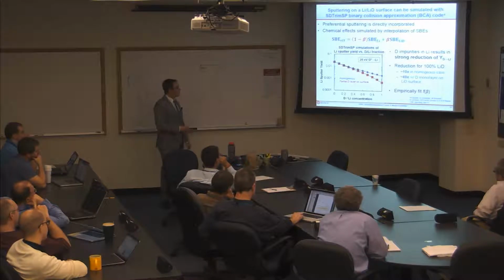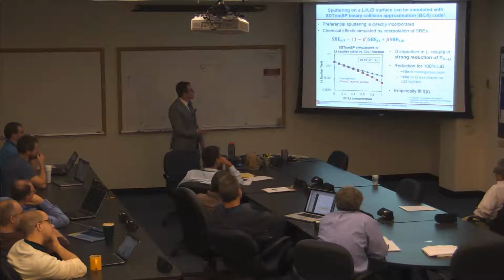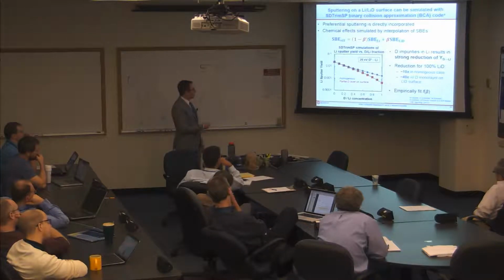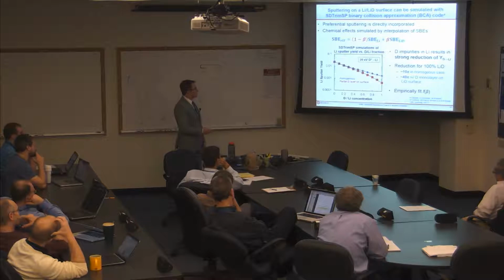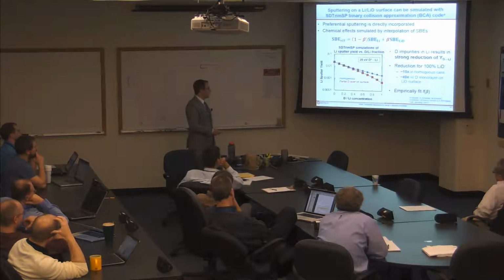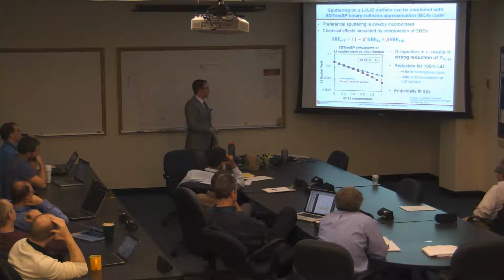And so what I did, for the purposes of changing the deuterium to lithium concentration, is linearly interpolate between the surface binding energies of lithium and lithium deuteride as a function of beta. So you incorporate the preferential sputtering, you incorporate the chemical effects, and you get this plot right here. This is for the case of 20 eV deuterium ions incident on a lithium surface at normal incidence.